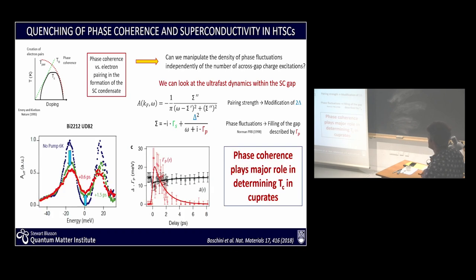And here is the work that Fabio has done now. You take an underdoped bismuth cuprate, and you start at low temperature, no pump, and you see a nice peak structure above and below the gap. I just remind you that photoemission measures only the occupied part of the spectral function, but if you have enough statistics and you divide off the Fermi function and resolution effects, then you can see a nice particle-hole symmetric gap and particle-hole symmetric peaks across this gap. Now you start pumping the system, and immediately, visually, you can see that the peaks are dropping in height, they're getting broader, there is not much of a shift in the gap position, the gap is not quite closing, but you do fill the gap. And so immediately you could conclude that the gap is not closing, it's filling in.